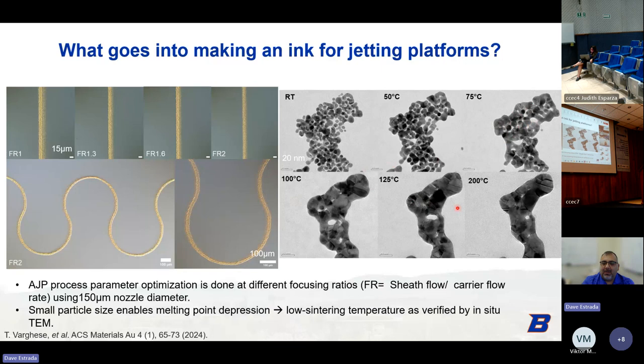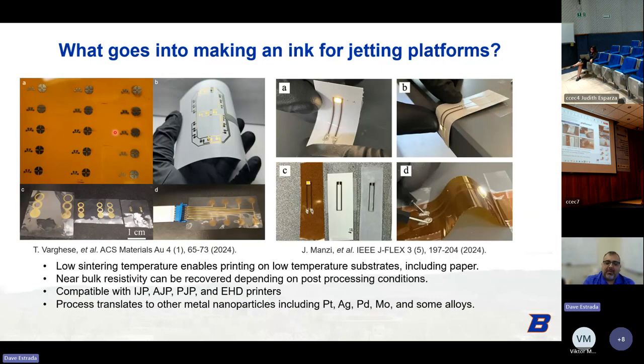And if we go all the way up to 200 degrees Celsius, we see very nice grain growth, which also correlates to nice electrical conductivity in our printed films. And so we've demonstrated different prints with this on different substrates, just various test structures on polyimide, an 8-segment display on paper, EMG sensors on PET. And then through the plasma jet printing process, we also can print and do self-sintering of this gold ink. Just electrodes highlighting connected to an LED, showing good flexibility and ability to print on plastics and paper.